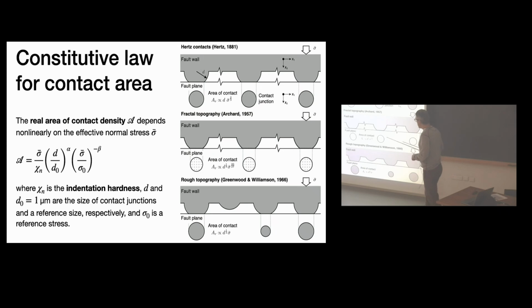And then if you make these spheres a little rough with a fractal geometry, the area of contact scales almost linearly with normal stress. It's the power 26 to 27. And if you randomize the initial height at which these spheres are pressed against each other, then the area of contact is linear to normal stress. For a long time, this model has been favored because people looked for linear models, but in reality, as we will see, this is in fact a better representation.